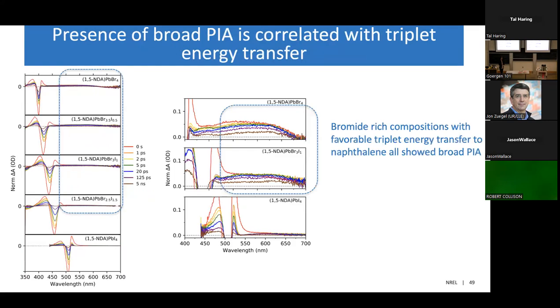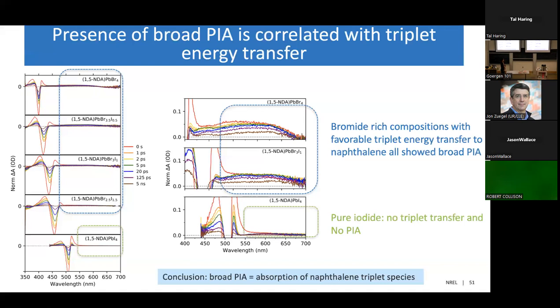Now here I have stacked the transient absorption spectra for all of the compounds, and I do apologize, it's impossible to see any sort of detail here on the left, but I'm showing a zoom in of some of the spectra here in the center. And what we noted was that for all of the bromide-rich compounds for which triplet transfer to naphthalene was favorable, we see this broad photoinduced absorption feature. However, for the pure iodide system where we don't expect any triplet transfer, there's also no photoinduced absorption. So at least qualitatively, we can conclude that this broad photoinduced absorption feature is related to the naphthalene triplet species